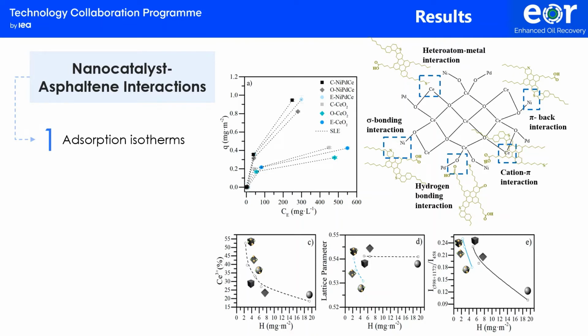Finally, according to the ceria 3+ content by XPS results, these parameters follow the trend: the higher the amount of ceria 3+ ions, the higher the affinity for asphaltenes due to the reduction of the asphaltene absorption potential. Also, the lattice parameter and the oxygen vacancies follow a similar trend between the doped and support materials.